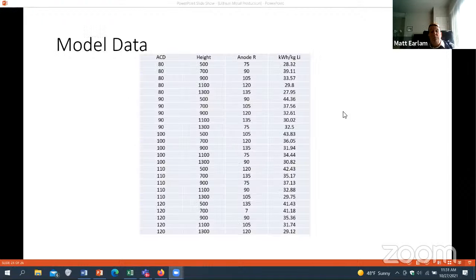Here it is in a table form. So they also adjusted the height of the anode and cathode pairs in their model. That's important because of the gas lift action that takes place, and also if they run a constant load, that changes the current density on the anode to a smaller current density, which means that you have less gas production per square centimeter. But you can see what they end up with is a situation where the kilowatt hours per kilogram of lithium is about 28.